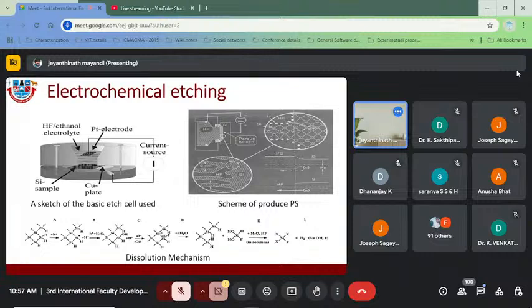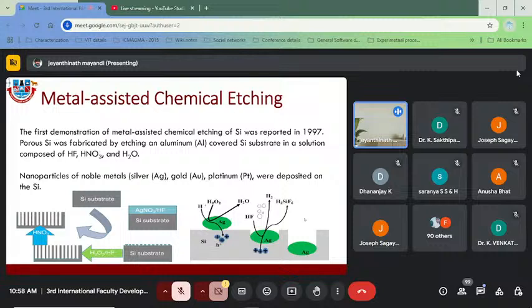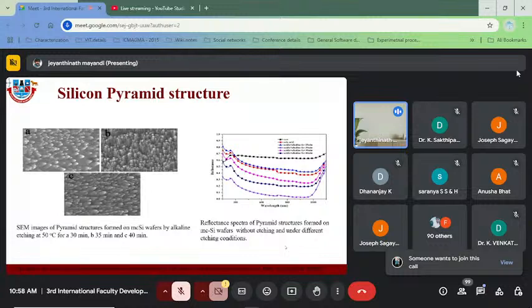And generally electrochemical etching is a well-known technique where you put your wafer on top of a copper plate, and then you put in an HF based electrolyte, and then you apply a potential between the copper electrode and the platinum electrode in the electrolyte, so that you start to etch the silicon wafers in a certain manner. And for metal assisted chemical etching, you throw some nanoparticles of silver or gold or any other metals on top of the silicon wafer, and you use HF, and then it starts to etch the interfaces of the nanoparticles that are lying on the silicon surface, and this will make nanostructures of pillars.